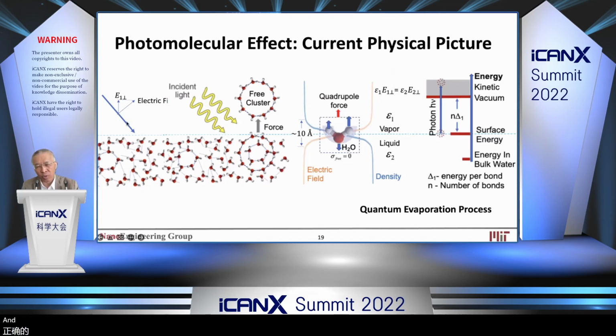And so in this case, electromagnetic wave is a transverse wave. And when you have an angle, then there's the electric field perpendicular to the interface. And when you have an electric field perpendicular to the interface, the Maxwell equation says the displacement field is continuous. So dielectric constant epsilon1 times field equals epsilon2 times field. But epsilon1, epsilon2 at visible light, they differ by a factor of 2. So over a distance of a few angstrom across the interface, there is a factor of 2 of electric field change. And now if I have a polar water molecule, which is 1 angstrom, right?